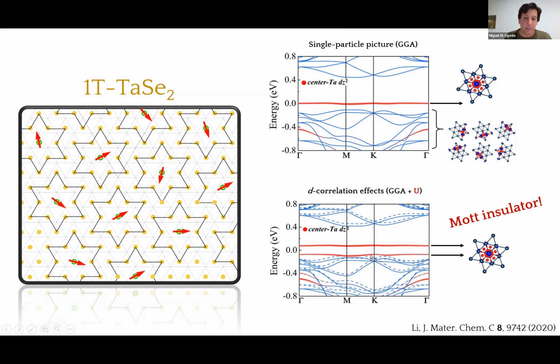And therefore, this material in principle is a Mott insulator with one subband totally full and one subband totally empty. But both of them, and this is important, should share the same orbital texture and should be localized here at the center of the Star of David. And that's an important detail, as I will show you in a second.